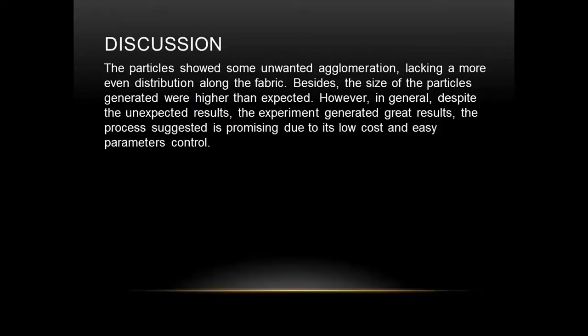Despite the success of the fabrication and impregnation method, not all the fibers of the fabrics were covered by the copper particles. We were able to notice it visually too. So some adjustments must be done to improve it. One of the main problems that we see is that the particles tend to agglomerate, affecting the efficiency and dispersion over the entire mask, similarly to the results obtained in other experiments, where the metal particles were unevenly spread across the test surfaces.